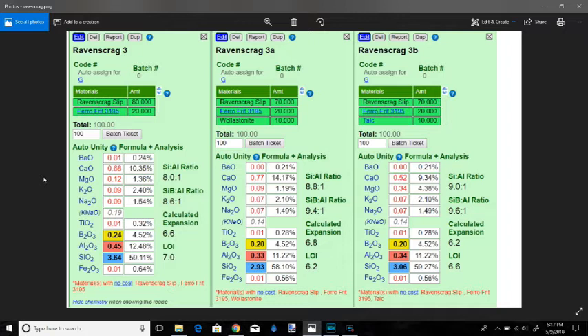So here's a picture from my Insight Live account, and this is just an example. The main sourcing material for the glaze is Ravenscrag slip, which is really nice. It's basically a pre-made glaze. So you enter that in, and then frit. That's basically going to act as our flux. But as you can see, this basic batch, the calculations come up to this.